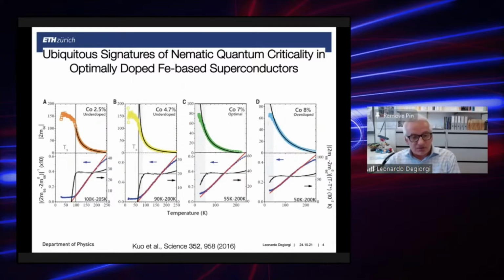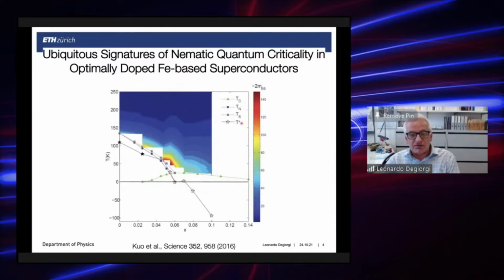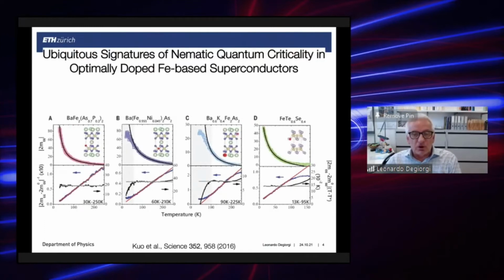Such a nematic susceptibility turns out to diverge in a Curie-like fashion. And if you plot the Curie temperature, the T star here, as a function of doping in this diagram, you see that it crosses the doping axis quite in coincidence with the optimally doped regime, which led to some conjecture that nematic quantum criticality may be very important here as far as the pairing mechanism is concerned, and eventually in order to enhance Tc. Now, it was also found that these behaviors occur in iron-based superconductors for several different families, and all the way up to the optimally doped regime.